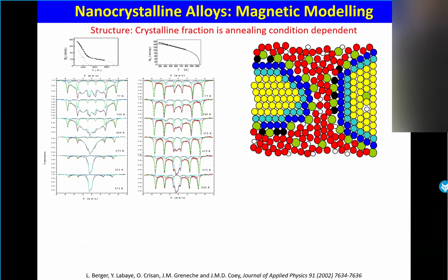And by doing some in-field Mössbauer experiments, it was possible to see that you have ferromagnetic grains, you have the ferromagnetic matrix, but you have non-ferromagnetic interfaces. They have a kind of spin-glass-like behavior because the magnetic moments are totally disordered. Okay, so it is possible to correlate with magnetic measurements.